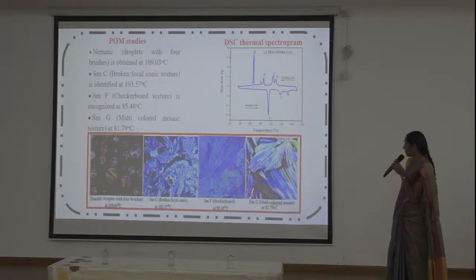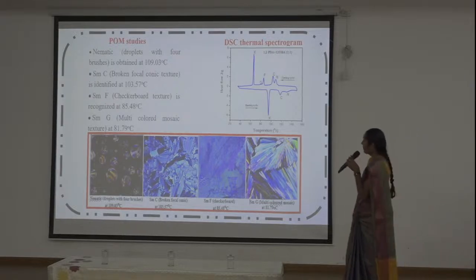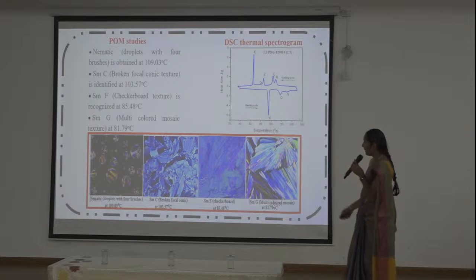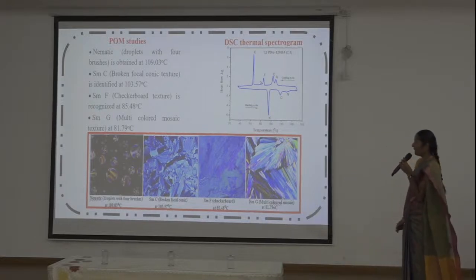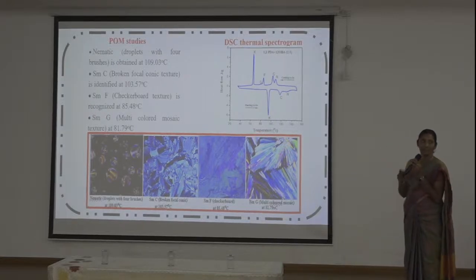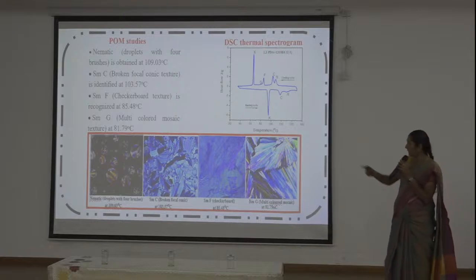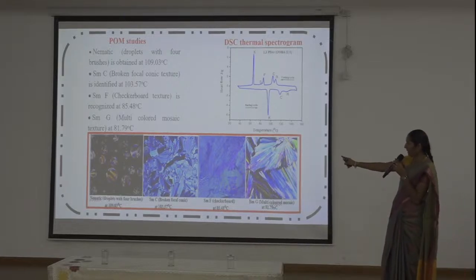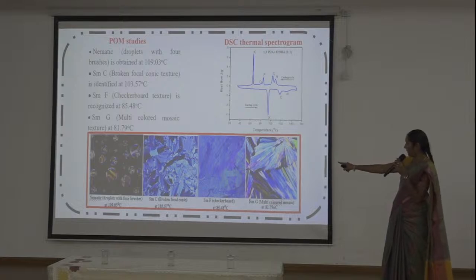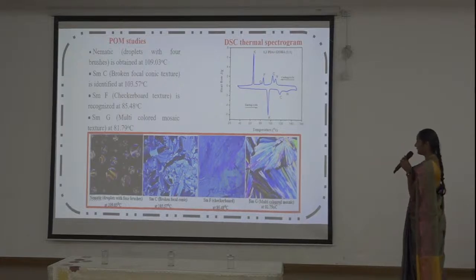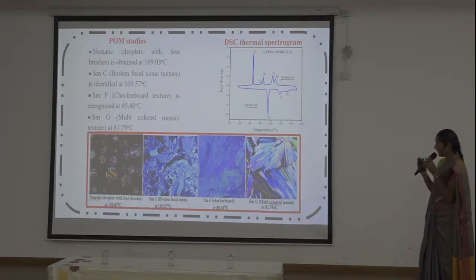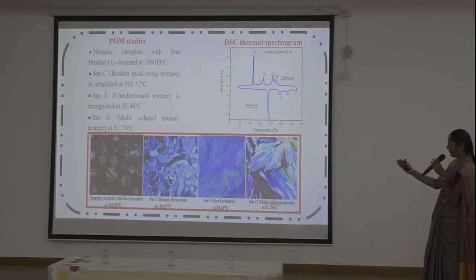At 109.03 degrees, there are many different types of nematic phases, droplets, thread-like patterns. There are colorful patterns observed when cooling the nematic phase near the liquid at 109.03 degrees centigrade.